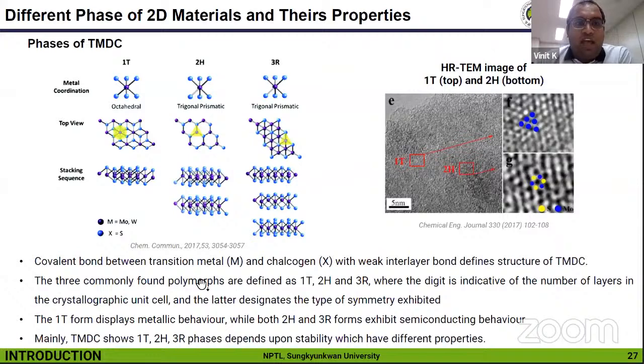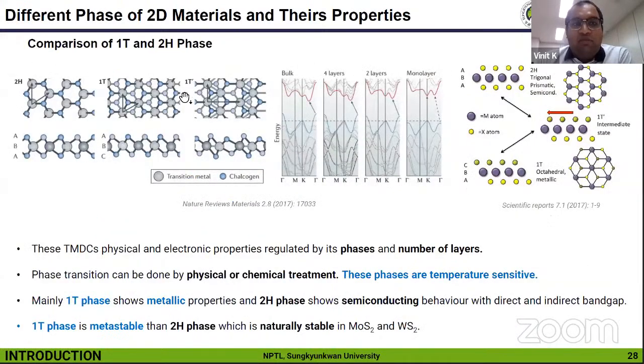Thank you so much. So, as shown in this figure, there are many phases like 1T and 2H. Basically, 1T is the metallic phase, so what we get in this case is the 1T phase. As compared with 2H, 1T is a relatively metastable phase, and 2H is naturally stable. Also, these phases are very temperature sensitive.